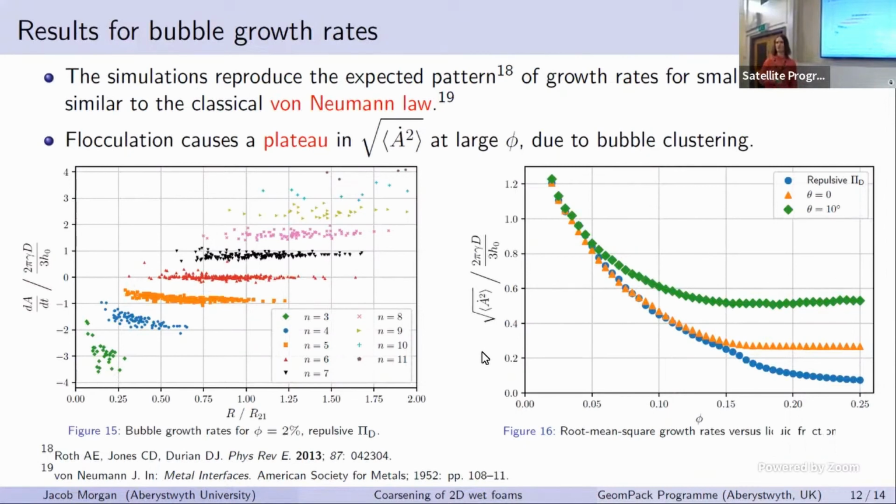That disagreement just comes from the finite film thickness, and possibly the definition of how we measure the contact angle as well. We fit circles to the film interface and to the plateau border interface and see at what angle they meet, which comes from a paper by Denkov, and I think is almost the standard one, although I know that there are other ways of doing it. It depends on where you choose to consider there is a transition region. But we can talk in detailed aspects later.